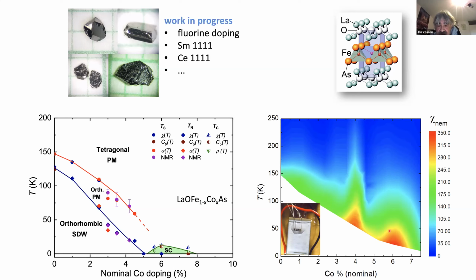So there's this ongoing discussion forever whether this nematicity is driven by the lattice, so that you just have a silly structural transition, or whether the electron system by itself wants to form a kind of quantum liquid crystal, and therefore you get this very strong nematic susceptibility that you see in the resistivity, which is a property of the electrons, right? You really look at the electron system. And they're always kind of coupled, right? So when the nematic susceptibility, which is purely electronic, starts to grow, at some point there will be a critical temperature where the lattice starts to communicate with it. And then it's not very surprising to find that it turns into, as I remember it, a first order structural transition from tetragonal to orthorhombic.